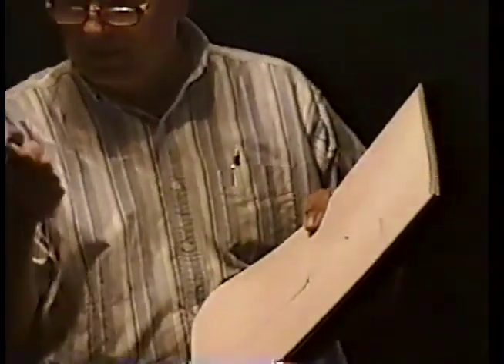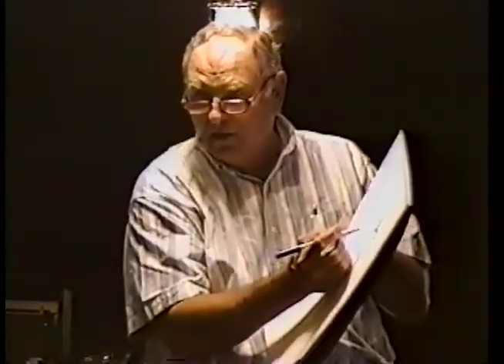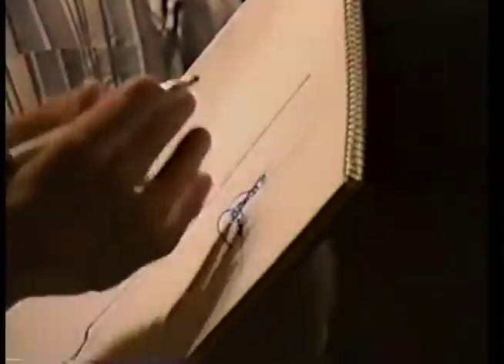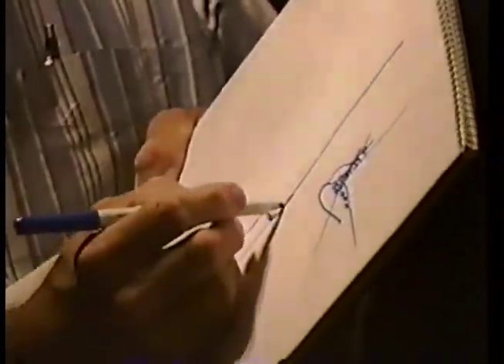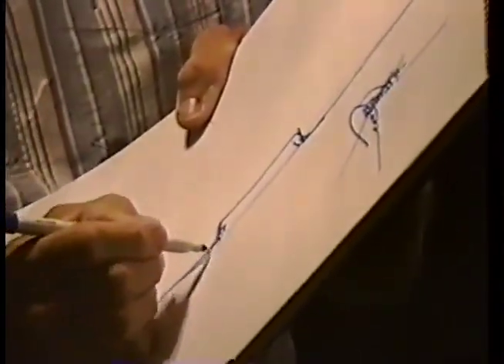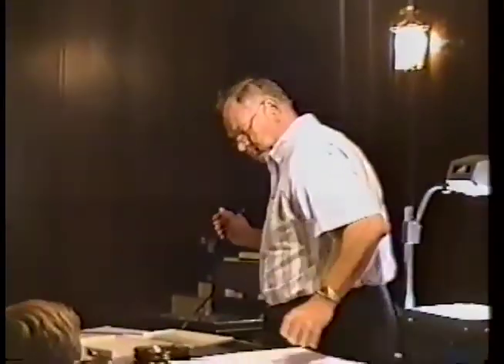chrome will not plate. And as you see on that test coupon, there are little balls. That's characteristic of chrome plate. It plates in little balls. So when it gets to a sharp corner, it tends to plate away from that corner as it's laying down its layers. And you end up with a big corner out there that then breaks off. It'll just come right off of itself at that corner, exposing that corner to more attack, or higher wear than the rest of the bore. So all of the edges must be broken down in radius so that the chrome will actually plate around it without building up. On the diesel locomotives as well as on the large Cooper two-cycles, it's absolutely critical that all of the edges are broken.